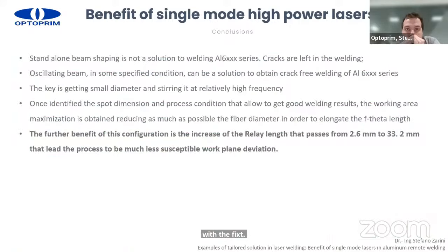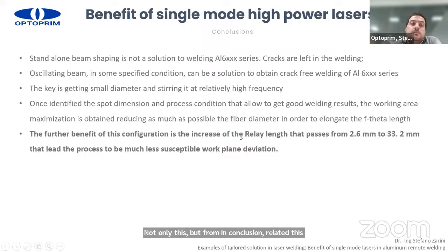Not only this, but in conclusion, related to this application, this is not the only biggest benefit; it is remarked, in the last sentence of this bullet point, the fact that with this other type of configuration, we can move the Rayleigh length from, let's say, 2.6 millimeters up to 33 millimeters. What does it mean? First of all, we become much less sensitive to eventual focus shift. Secondly, we can be much less sensitive to focus variation of the working plane, especially if we weld thin aluminum foil. And this is a really huge benefit from a practical point of view, from a production point of view.